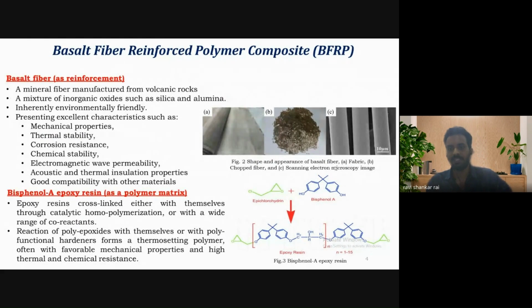Here the matrix material used is a polymer, which is a bisphenol A epoxy resin. And obviously we have added some hardener along with this bisphenol A epoxy resin. We use epoxy resin because it has the ability to undergo homopolymerization and has a wide range of co-reactants. And also it has a linkage structure which can combine with other particles and make cross-linking structures.